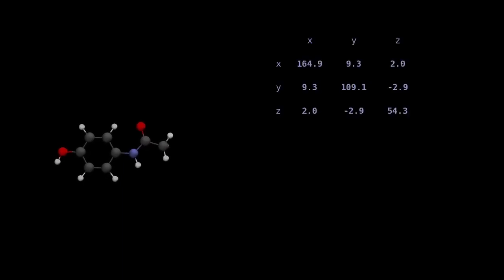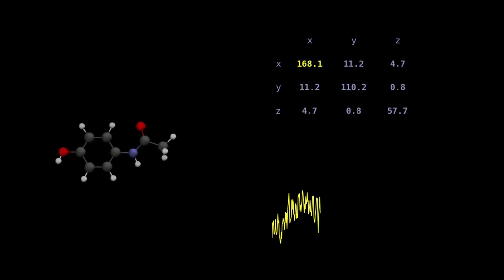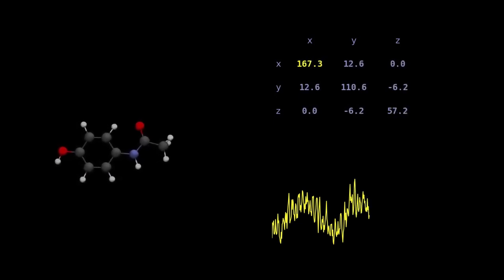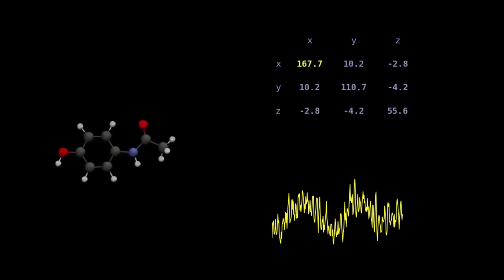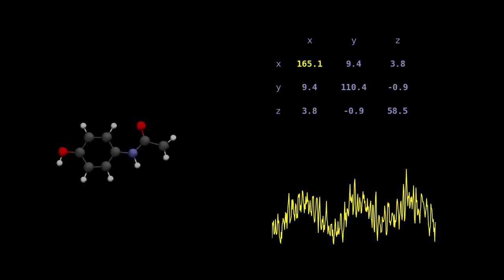To simulate vibrational Raman spectra, one way is to run a molecular dynamics trajectory, on top of which one computes polarizability tensors. Each component experiences periodic variations over time, which are then used to compute the Raman spectrum through an autocorrelation function formalism. Such calculations are typically very expensive, as tens of thousands of polarizability calculations need to be carried out. Furthermore, such samplings contain a lot of similar-looking structures.